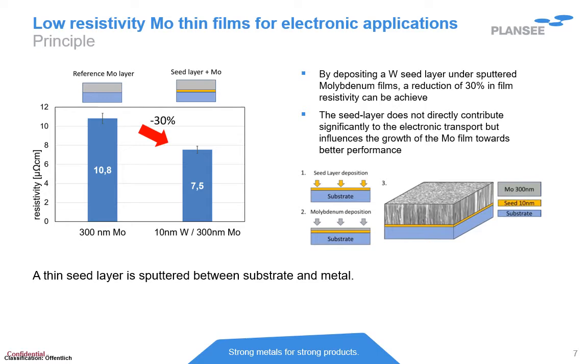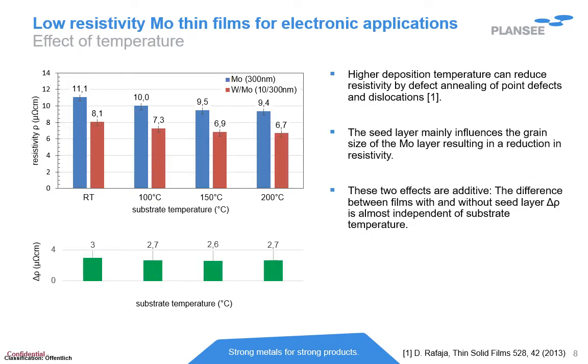This is possible because this thin seed layer, which can have a thickness of about 10 nanometers, for example, strongly influences the microstructure and domain size of the top molybdenum film, which results in a strongly increased conductivity of this molybdenum thin film. This approach was described about 20 years ago for tungsten titanium films for microelectronic applications, but here it could be shown for the first time that it also works for pure molybdenum thin films by applying such thin tungsten seed layers below the molybdenum layer. This effect